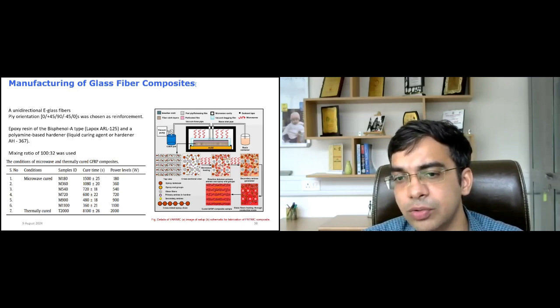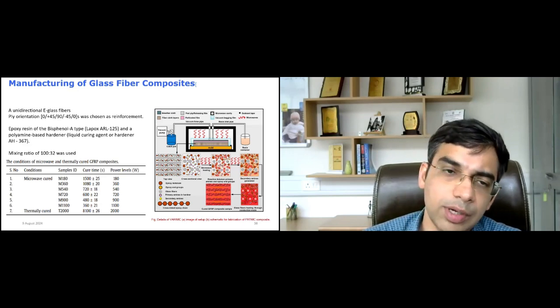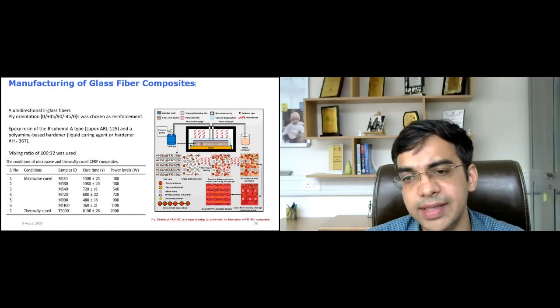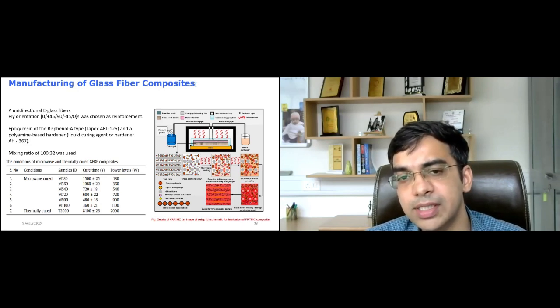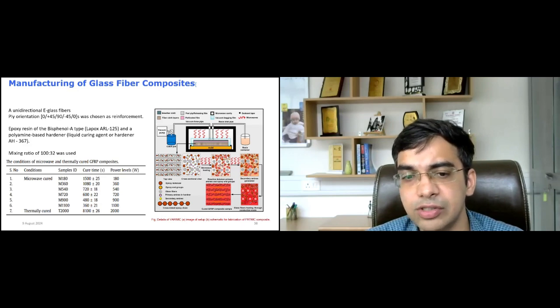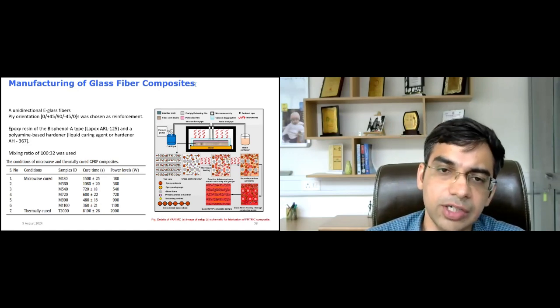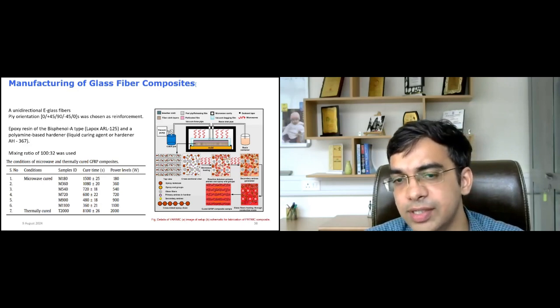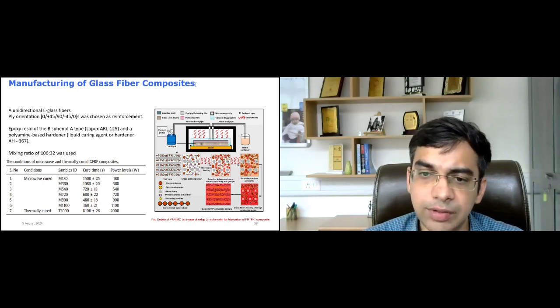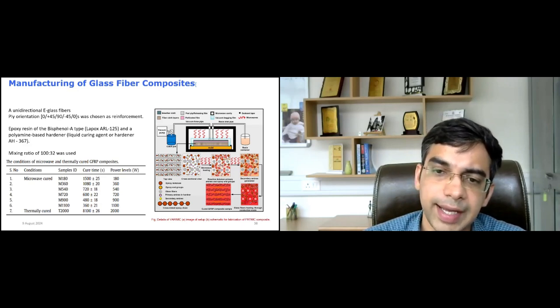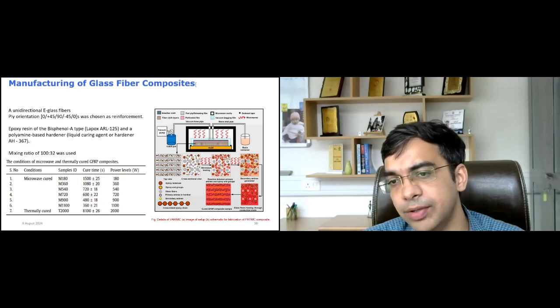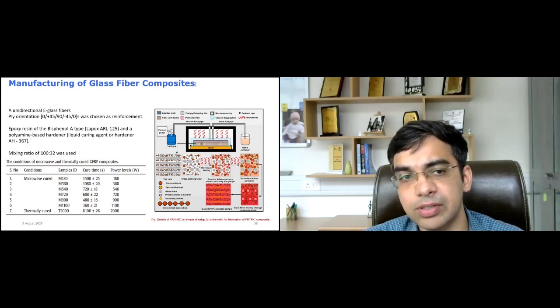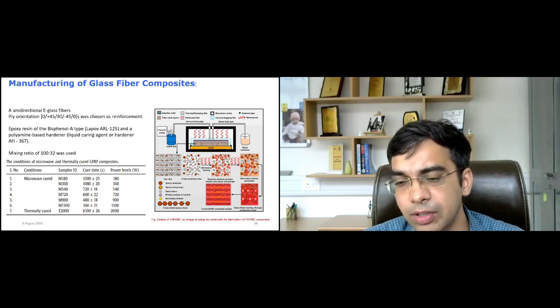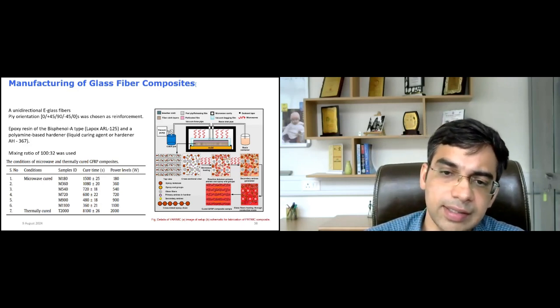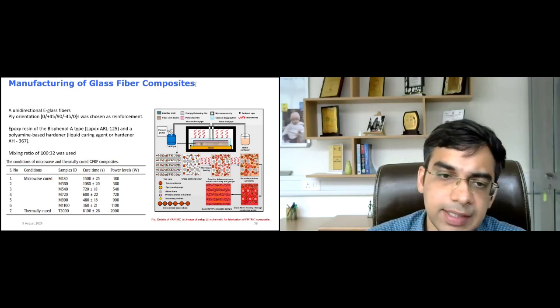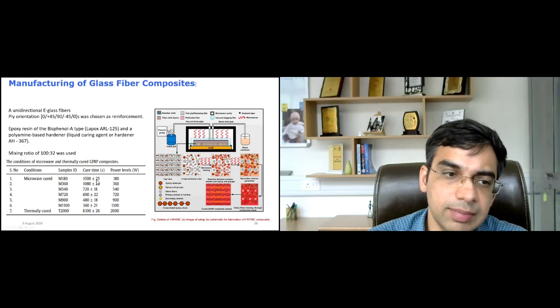Now here epoxy is again unique because epoxy molecules are also polar molecules, and polar molecules are very good when they interact with microwaves. So as we know, epoxy is one of the popular matrix used in structural composites, as no byproducts are generated during the curing of epoxy, and it is widely used in several applications. So that was another motivation of utilizing epoxy in this case. And as the epoxy molecules interact with the microwave, the curing sets in because the hardener is already mixed in. And because of the volumetric heating or volumetric interaction characteristic of microwave, we could observe that curing can take place in this amount of time, as shown in this table here.